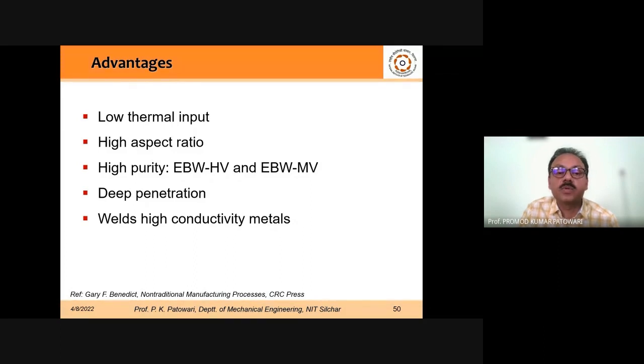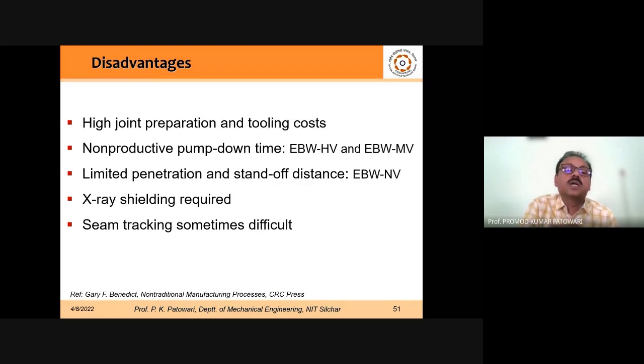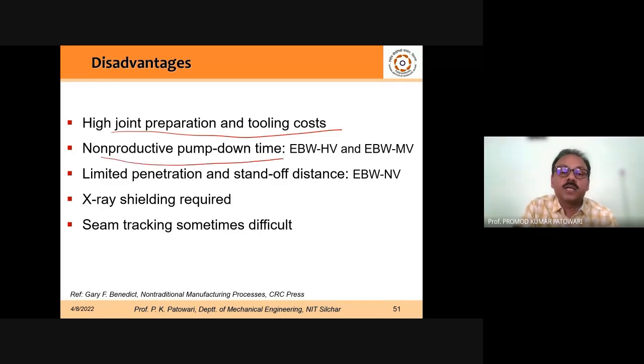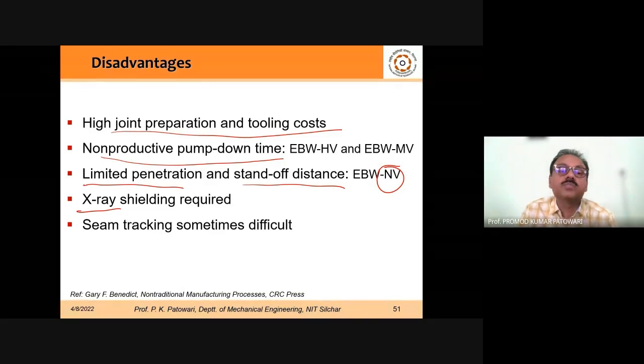These are the advantages of electron beam welding: low thermal input, high aspect ratio, high purity, deep penetration, and it welds very high conductive materials also. That is again another advantage, because you have to win over the conductivity. Before the conductivity dissipates the heat, you just complete the cycle. It should be that fast, and that's why we require the shorter pulses. The disadvantages: the high joint preparation time and cost, the non-productive pump down time, limited penetration if the stand-off distance is high, or even no vacuum. Then X-ray shielding is required, because of the interaction of the electron beam with the workpiece material. Some X-rays may come, so it requires proper protection. And seam tracking is sometimes difficult, because it is inside the vacuum chamber.